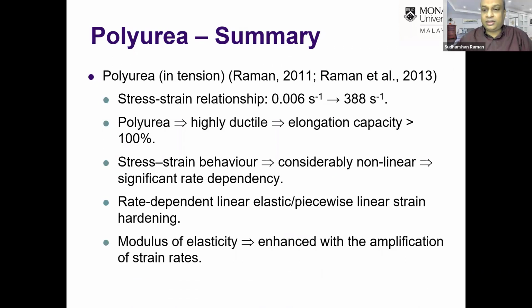So to summarize the major findings from this work, the strain rate range that we tested went from 0.006, which represents the quasi-static condition, up to about 388. The polyurea is highly ductile, with an elongation capacity of more than 100%. The stress strain behavior is considerably non-linear and exhibited significant rate dependency, and we have classified this material behavior as rate dependent, linear elastic piecewise, linear strain hardening material. One of the major observations is that the modulus of elasticity is enhanced with the amplification of strain rate, or the material stiffens when the strain rate is increased.